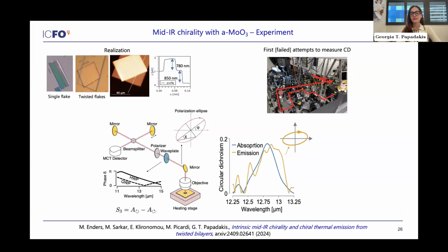These measurements, as I already said, are very sensitive. In fact, at some point we stopped having multiple people in the room, because if you have many people in the room doing the experiment, we also emit, or everything emits. So one solution is to purge. In our case, we didn't actually purge, so these measurements are without any purging, but basically you have to eliminate any gases. You have to keep everything around very cool in order to minimize the background thermal emission.